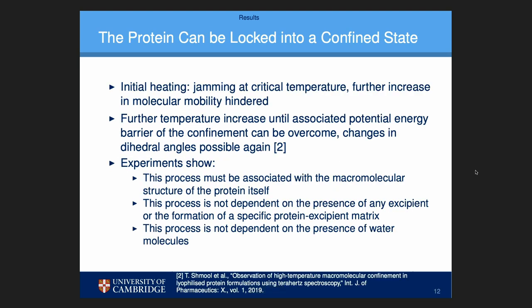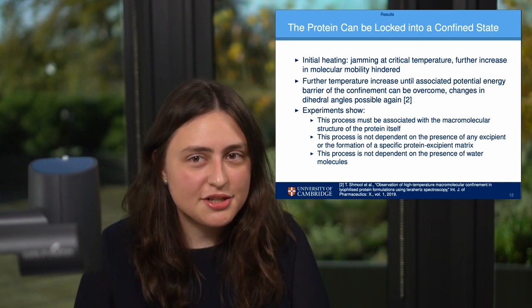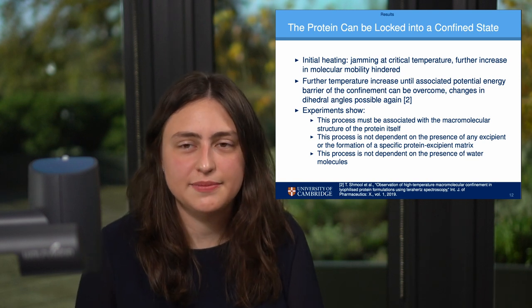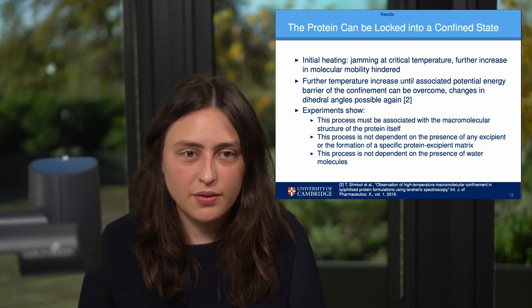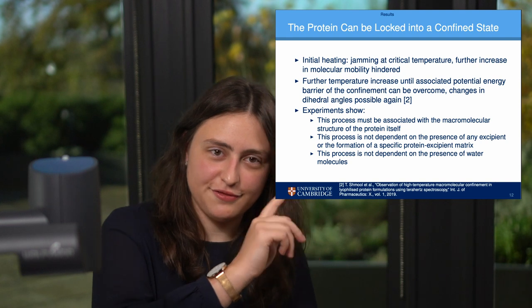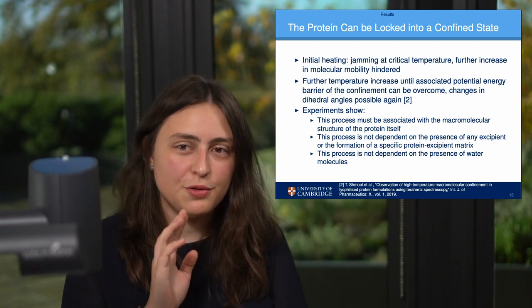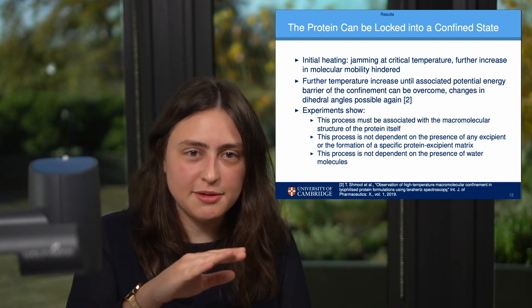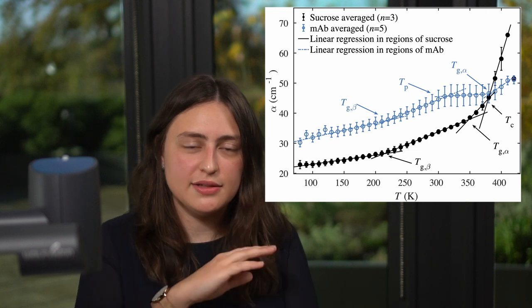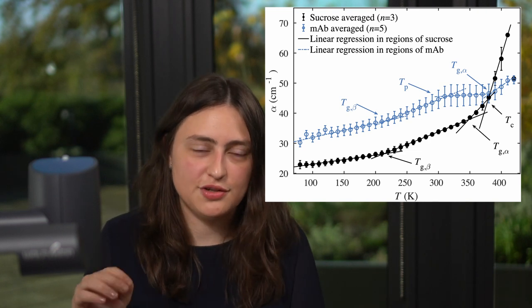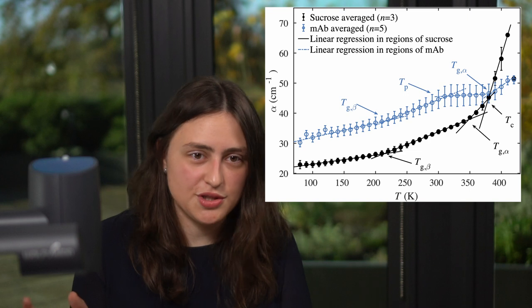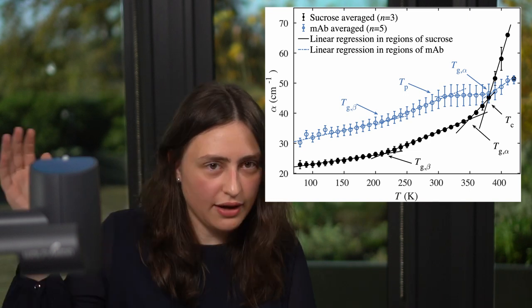This leads directly to the idea that the protein can actually be locked into a confined state. If we think back to the early results showing the increase in absorption with temperature — in small molecular drugs we get a steady increase to the transition temperatures, with absorption increasing all along. However, if we have a lot of antibody in there, we get a plateau.